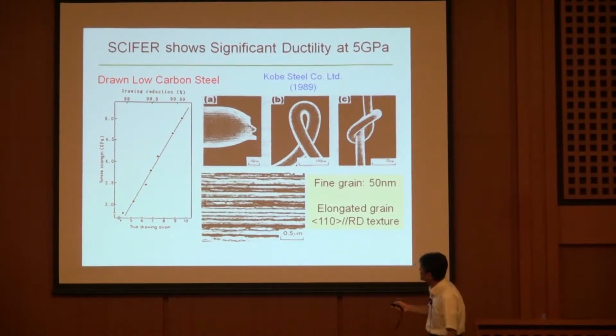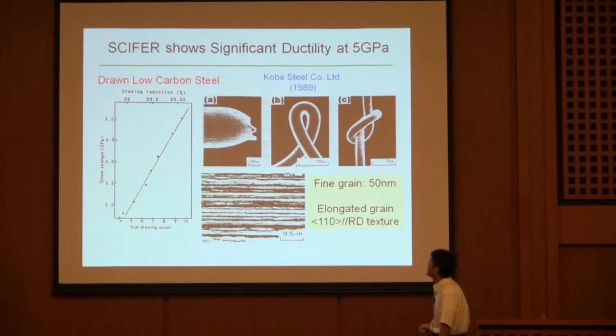And please look at this. This is the true drawing strain, and this is the tensile strength. So 5 gigapascal of strength is achieved by a 99.99 drawing reduction, a very high drawing reduction ratio. And this is the picture after the tensile test. This wire can bend, and this is a knot here.